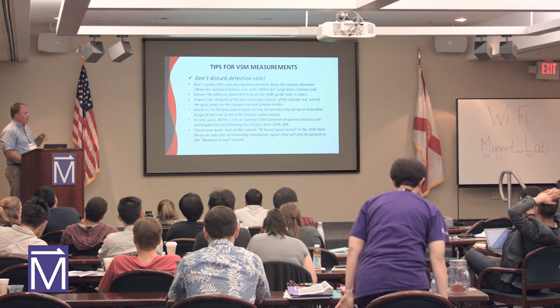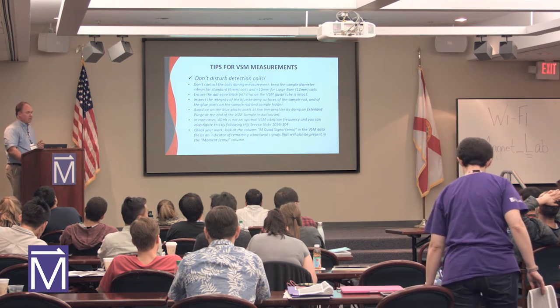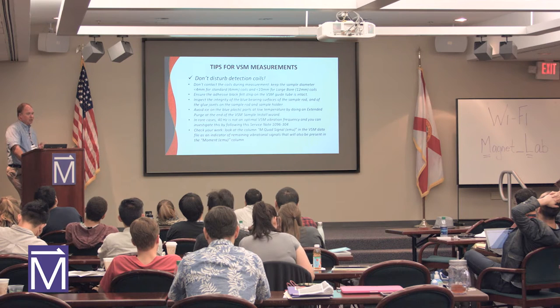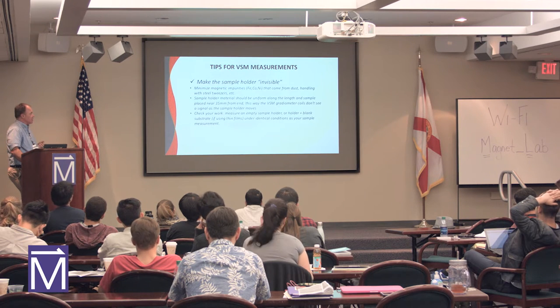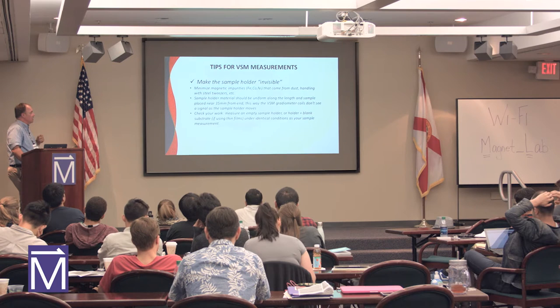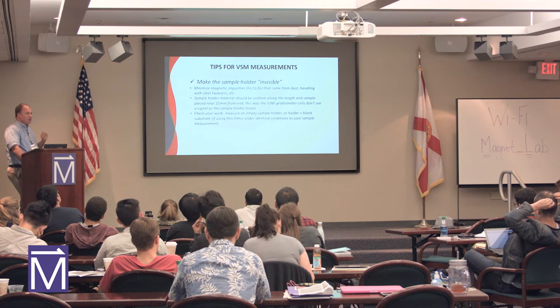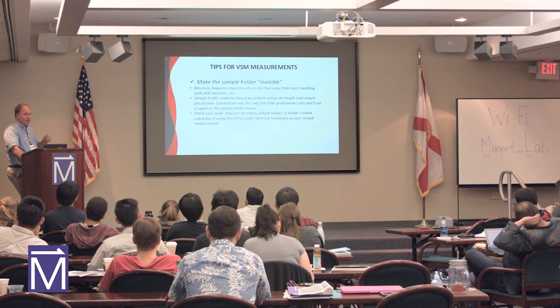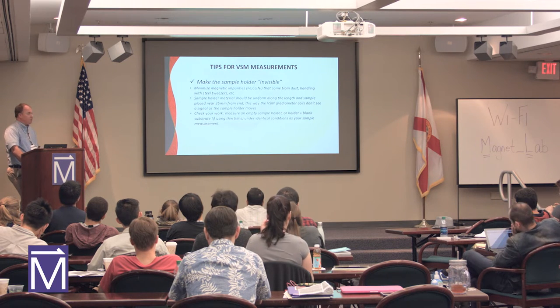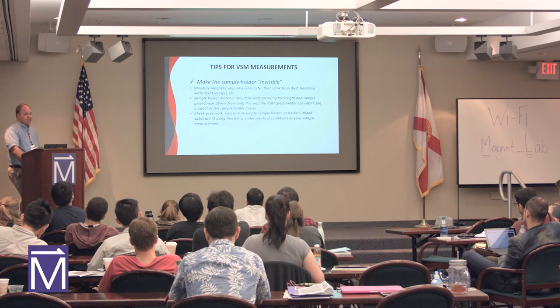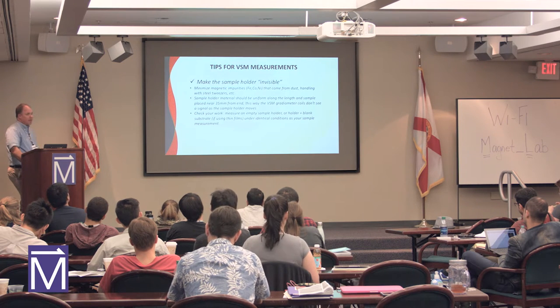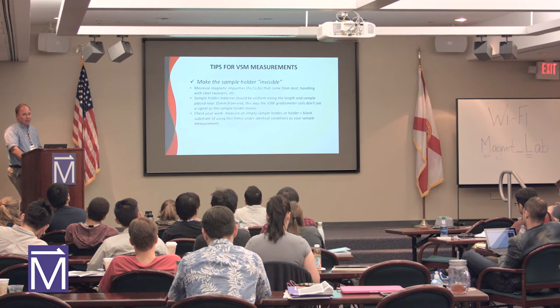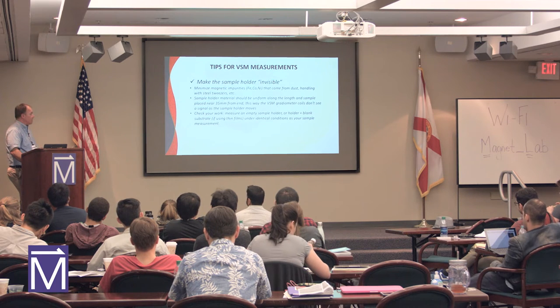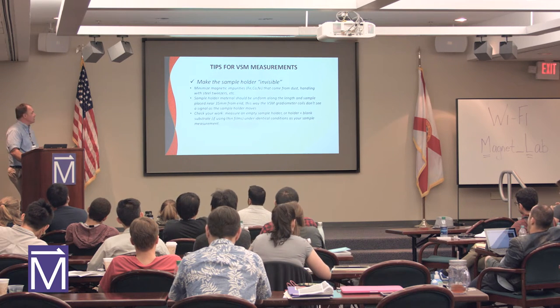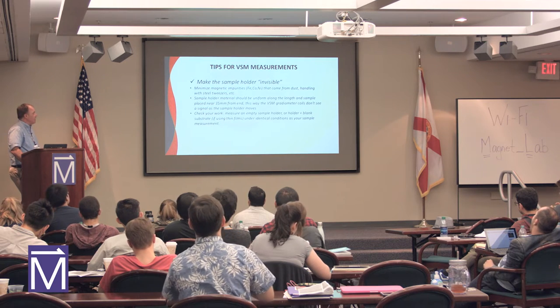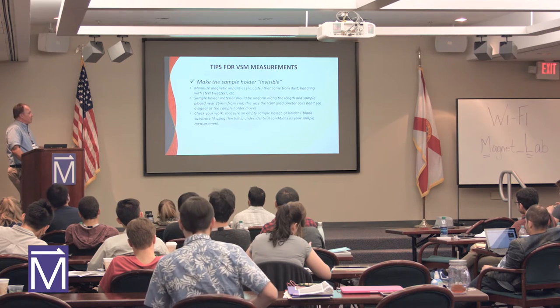There's a subtlety: if the 40 hertz frequency isn't correct, if there's some resonance, that might be an issue, and we've got an app note in the service bulletins that talks about that particular case. Make the sample holder invisible. Use non-magnetic tools when you hold your sample, because those may add contamination to your sample, right? There are some well-known papers where people made measurements and thought they had a discovery, but it was from the tools that they used and introduced into some of the nanomaterials that they developed.